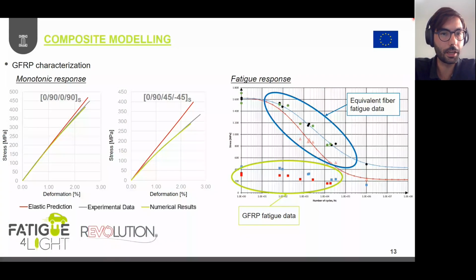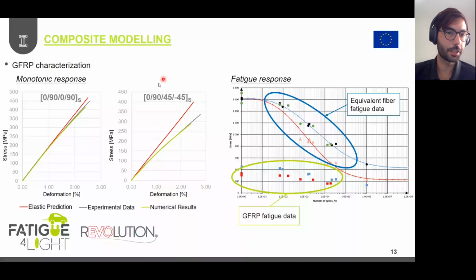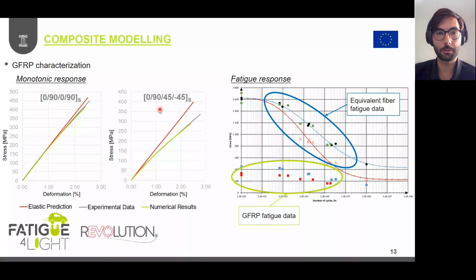So it's a highly efficient methodology, and not only 0 and 90 can be modeled. In the right-hand side chart, we can see that we are also getting really good results combining 0, 90, 45, minus 45 rotation. This rotation can be arbitrary and selected from the input data. And the good thing is that we don't have to recalibrate anything.